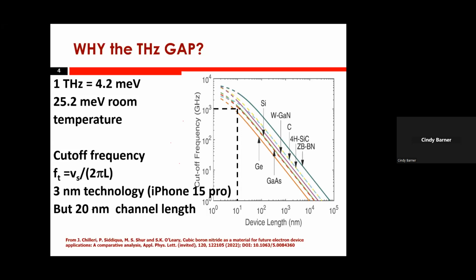On the other hand, as you see on this slide, it's hard to approach the cutoff frequency of 1 terahertz, even though some of these lines come close at about 20 nanometers or so. But in fact, this is the upper bound for the cutoff frequency. The actual cutoff frequency tends to be lower. Therefore conventional electronics is kind of running out of steam. Even though today we have 3 nanometer technology, like in the iPhone 15 Pro, for example, in fact the channel length is about 20 nanometers. So this slide is somewhere here. That's where the gap is.